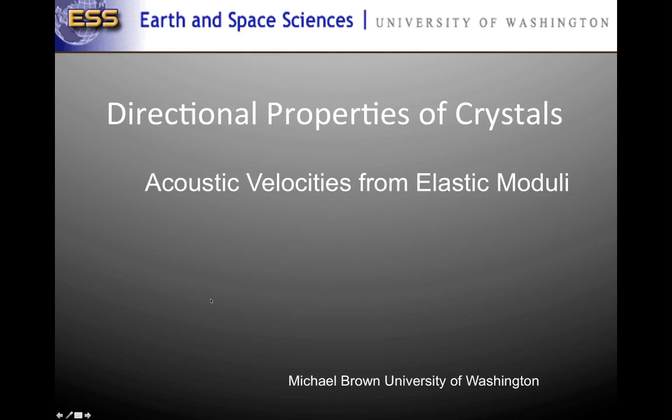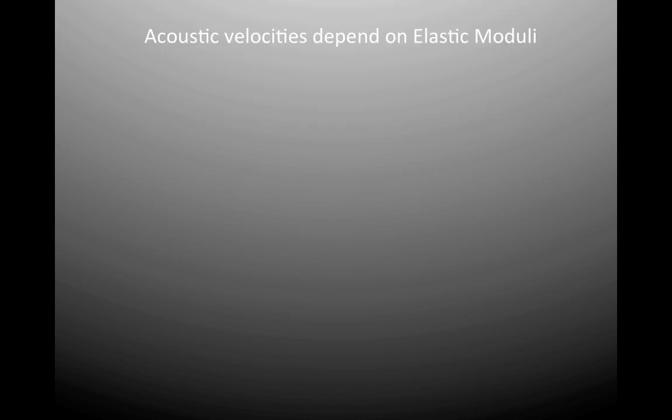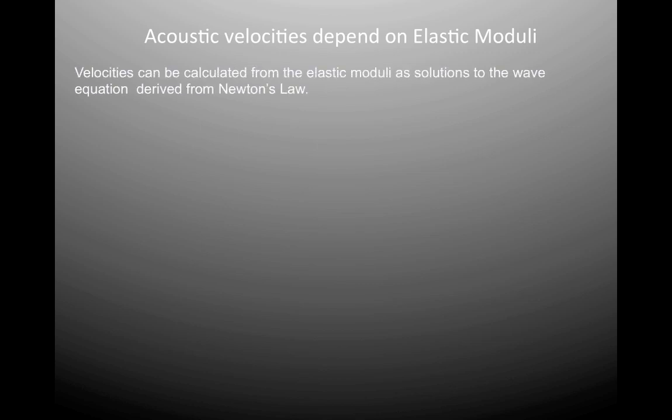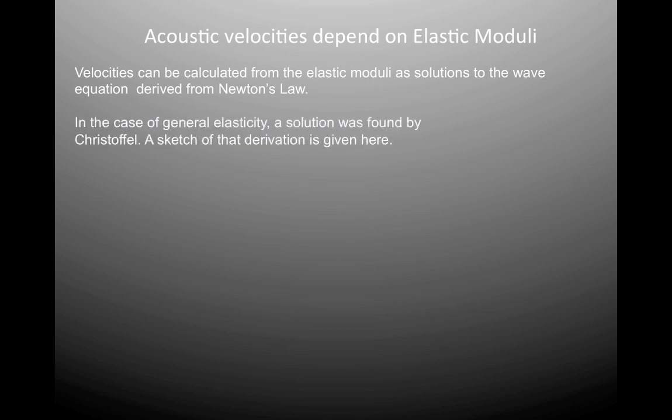In this video on directional properties of crystals, I want to talk about the connection between acoustic velocities and the elastic moduli. Well, the acoustic velocities depend on elastic moduli, and you can calculate velocities if you know the moduli, and they arise as solutions to a wave equation, which is based on Newton's law.